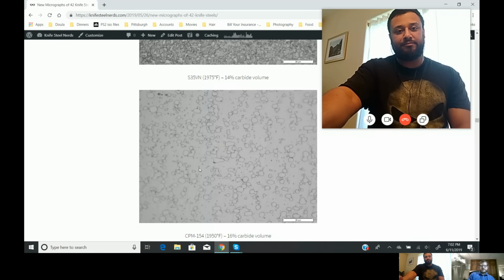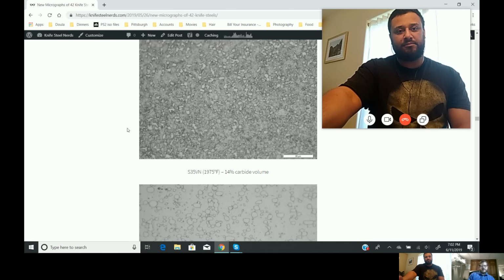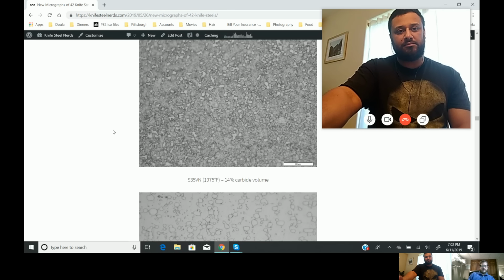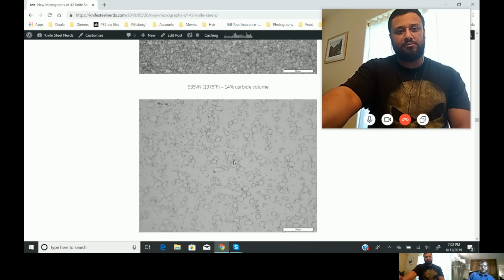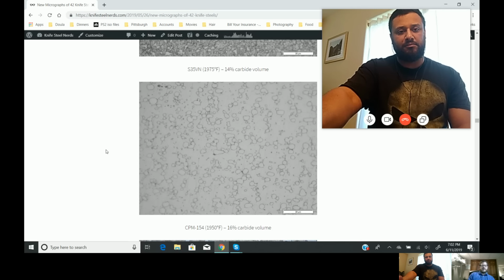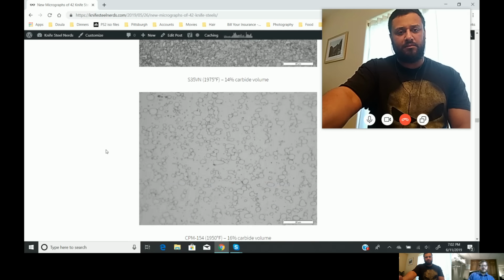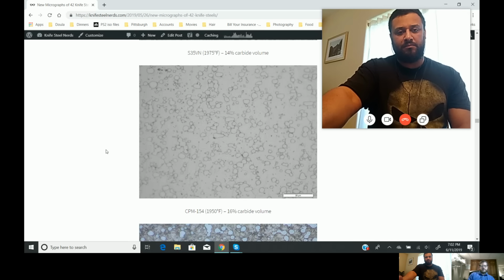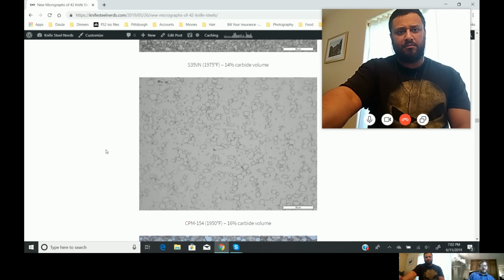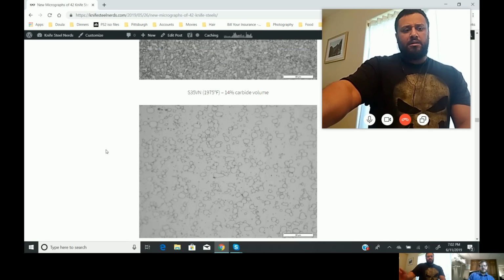CPM 154 has much larger, more spherical carbides. And so I think this is just a product of the carbide type, where S35VN has a combination of chromium and vanadium carbides. The CPM 154 is all chromium carbide. We talked about why those get bigger and coarsen more. In our toughness testing, the CPM 154 was tougher than the S35VN, which I still haven't been able to figure out why that was. And I wanted to test some more CPM 154 to make sure that it replicates. But yeah, for some reason, it came out tougher than S35VN.